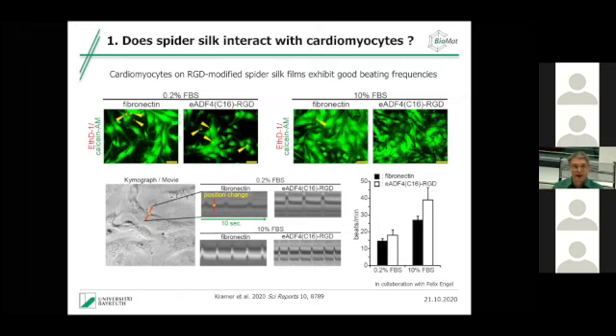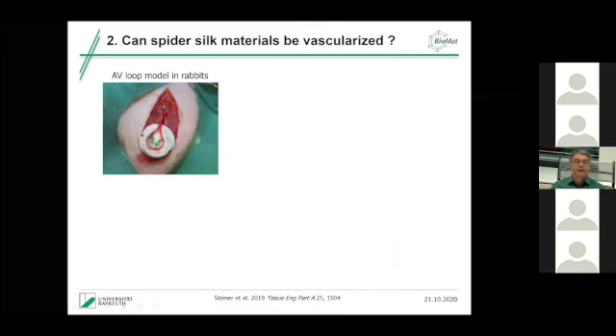And so we see here an increase in the beating rate already in 2D, and this is a very good sign, because this actually tells us the spider silk variant is even better than fibronectin. So for this first step, we have to go further ahead because we have to go into 3D. And if we want to have a really 3D working muscle, what do we need? Well, we need vascularization. So we need blood vessels to grow into the silk.